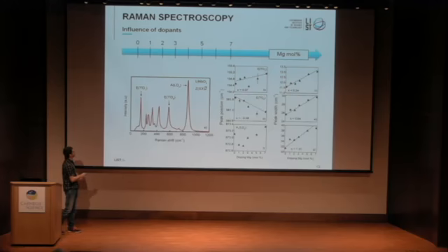I will focus on three modes, just their names: ETO1, ETO8, and A1(LO)4. You do not have to remember this. What you see is that with doping, the peak width of all these modes increases. And this is expected because you increase the disorder. You put magnesium in your sample, so the peak width increases.